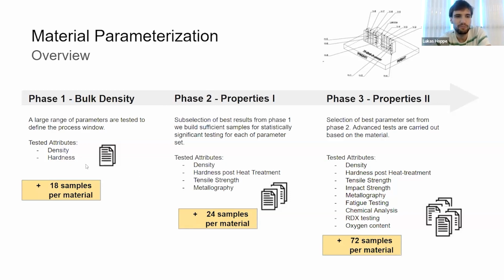So just looking at the CT scan is basically not enough for getting good density data, because this only shows you bulk defects that are visible to the CT scan. In this case, we're also doing micrography. So we're looking at much smaller details, which could be distributed more or less homogeneously throughout the part, which might be gas bubbles or other unwanted alloys or phases that might be forming. So we're doing pretty large blocks. We're doing a fairly large number of tensile tests to get representative results.